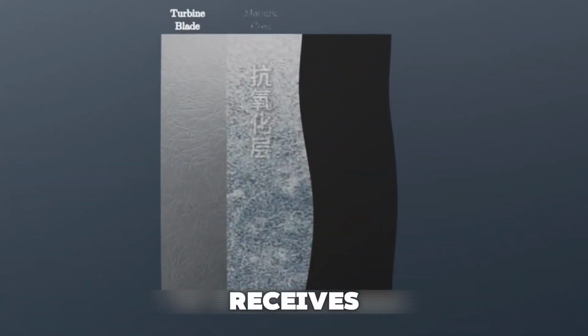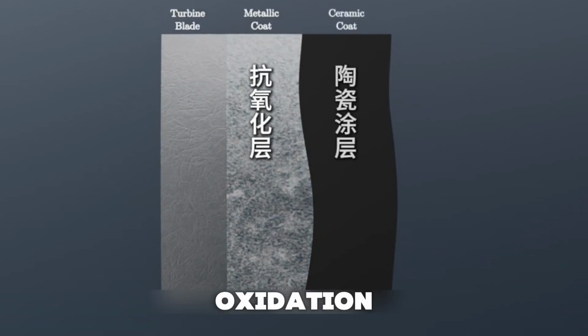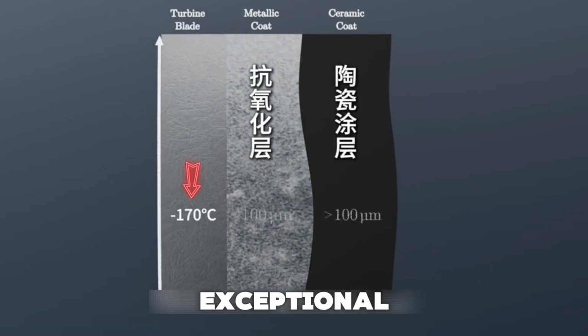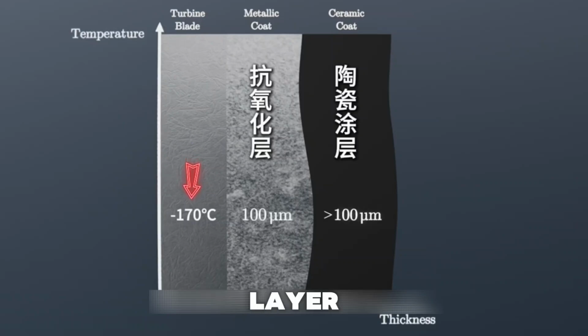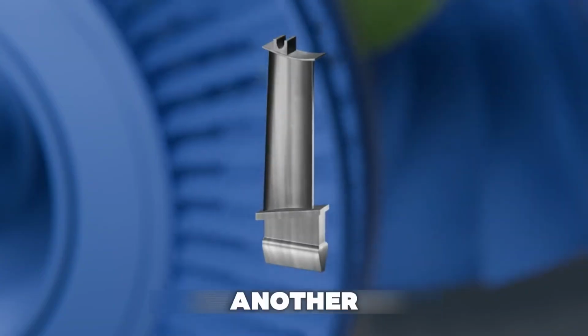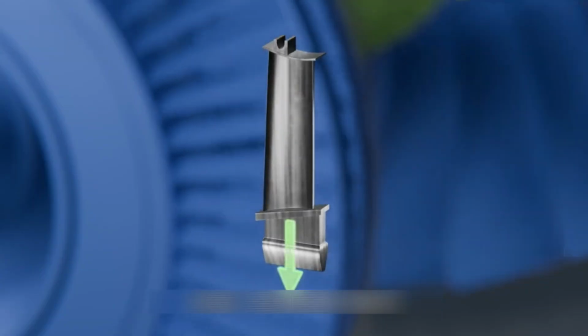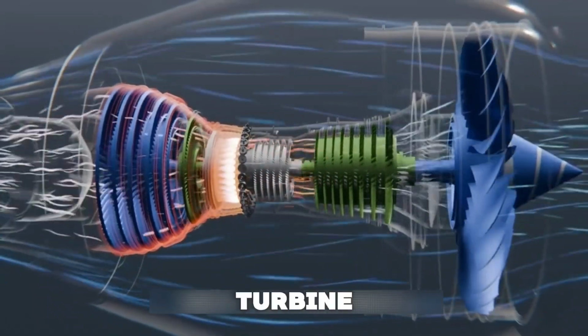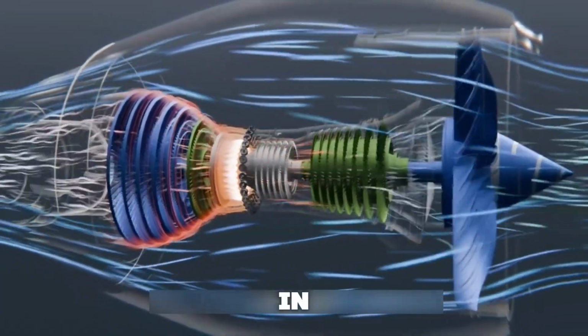Third, the blade receives two protective coatings. The first is a metallic coating that prevents oxidation. The second is a ceramic thermal barrier. Ceramics are exceptional insulators. This layer lowers the internal blade temperature by another 170 degrees. Together, these systems allow turbine blades to operate reliably in conditions that should be impossible.